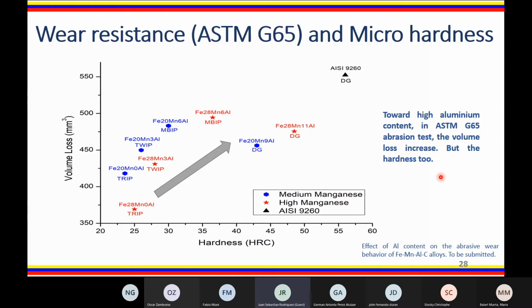It is important to appreciate that the hardness of this steel does not depend on the loss of volume. It can be seen that FeMnAlC steels of high hardness have the highest volume loss. It is also important to see that this is due to the increase in aluminum content. One of the explanations that we have for this behavior is based on the stacking fault energy. Increasing the aluminum content increases this energy. Therefore, this increase generates a transition from hardening mechanisms such as TRIP, TWIP, and MBIP, toward others with higher stacking fault energy, such as dislocation glide.